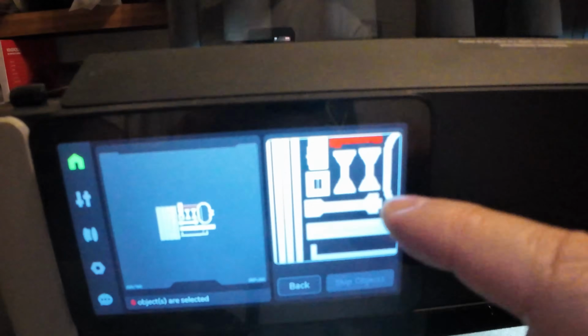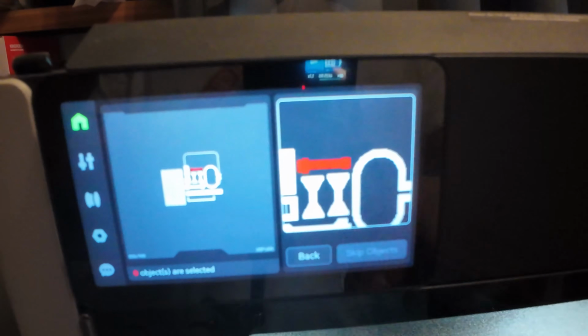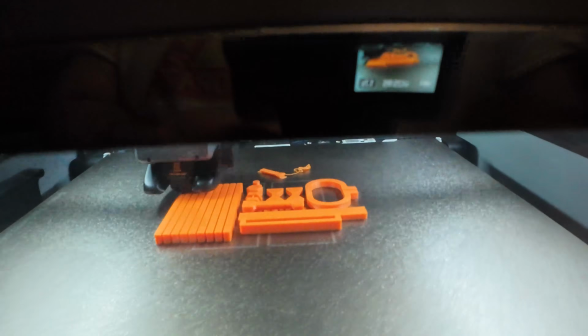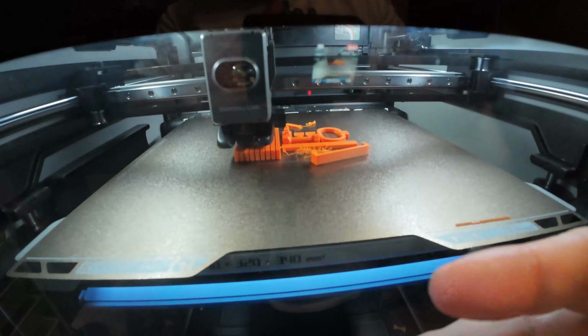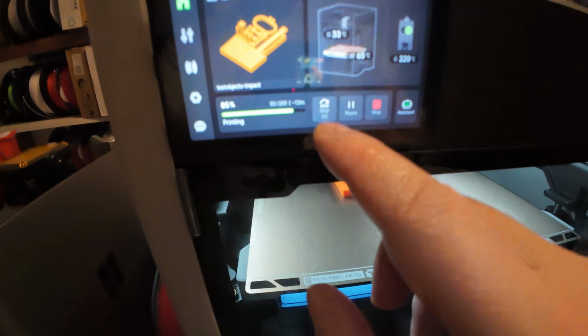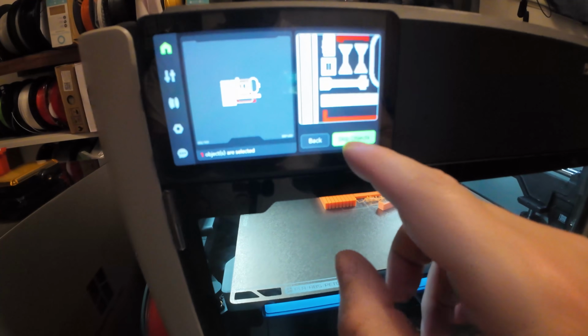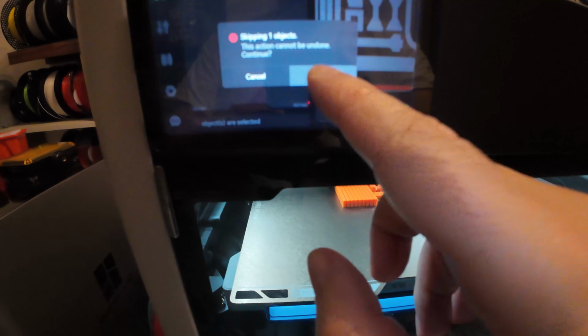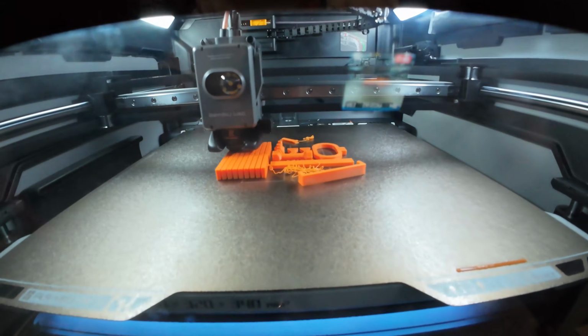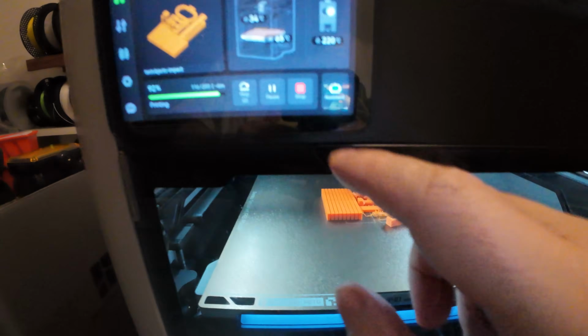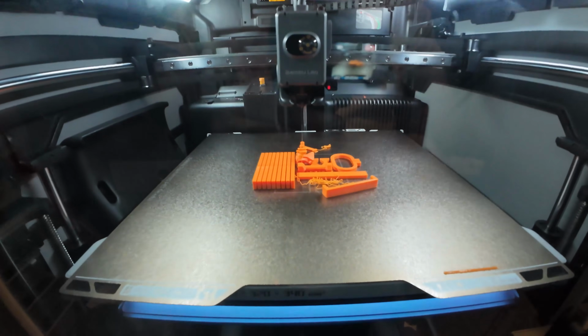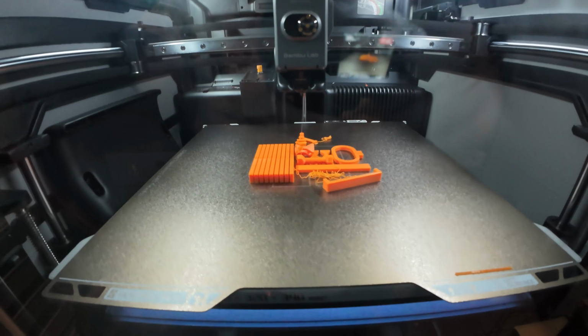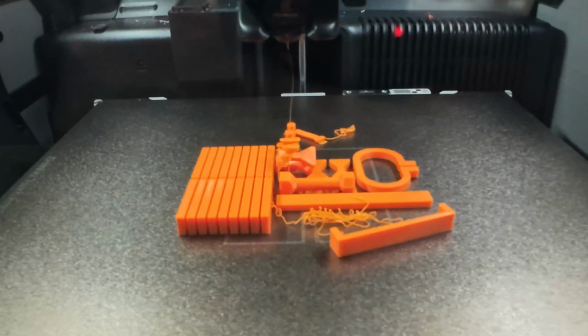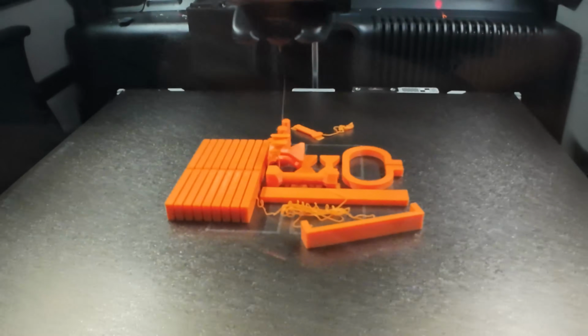In the second attempt, the horizontal shear test object was removed, but this time I'm skipping that object. A little bit later, another object was removed. This one is for the temperature test, so I'm skipping another one. After this, most of the parts were finished, but I noticed another one removed from the bed, and this time I stopped the printing. Usually I have great bed adhesion with this textured PEI sheet and PLA. It was cleaned with isopropyl alcohol, but let's check the bed adhesion.